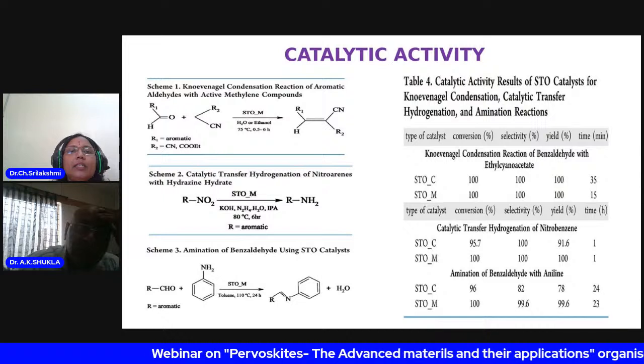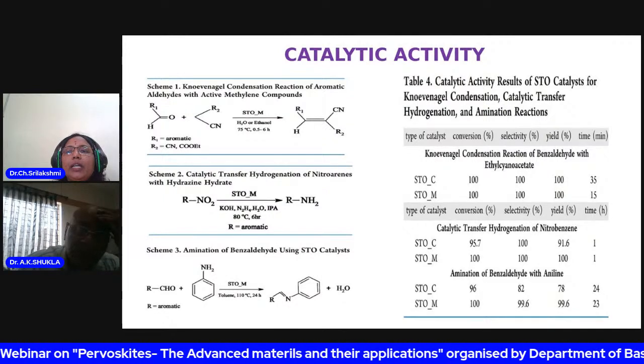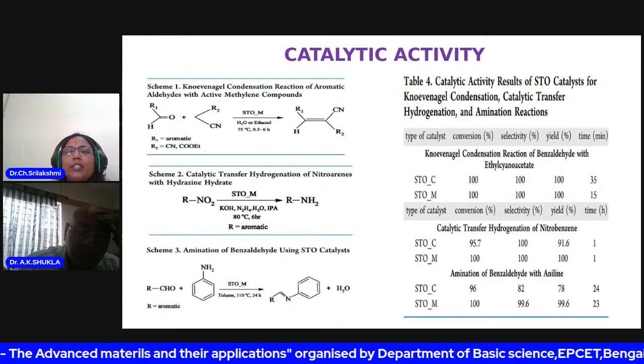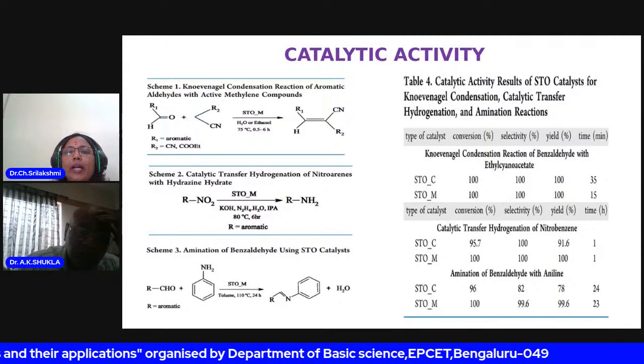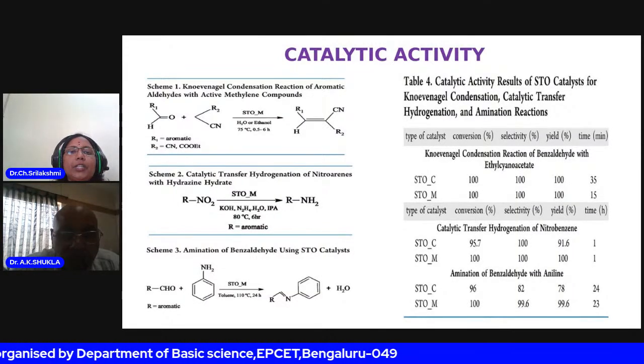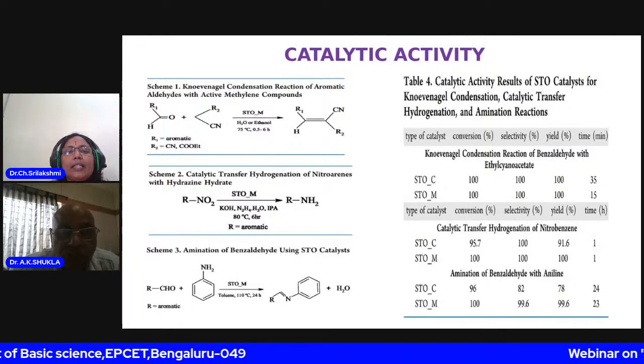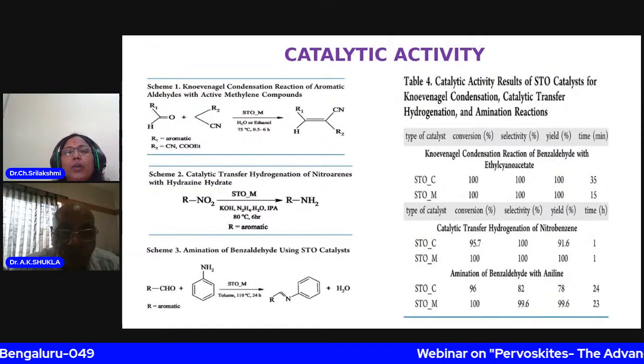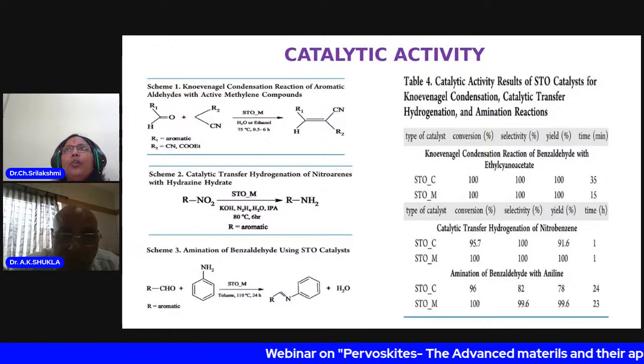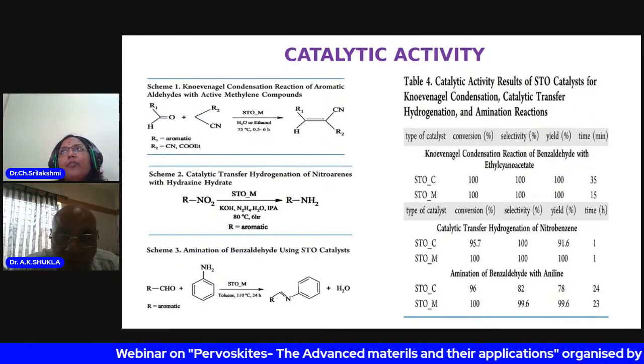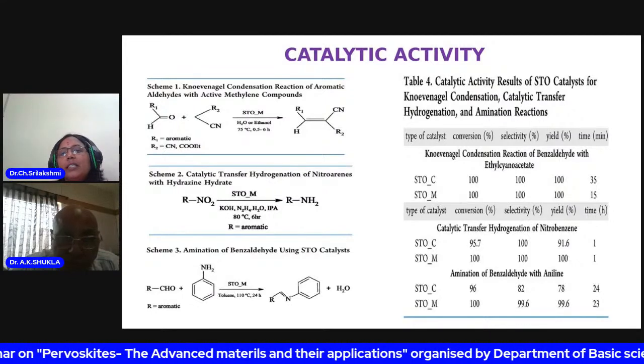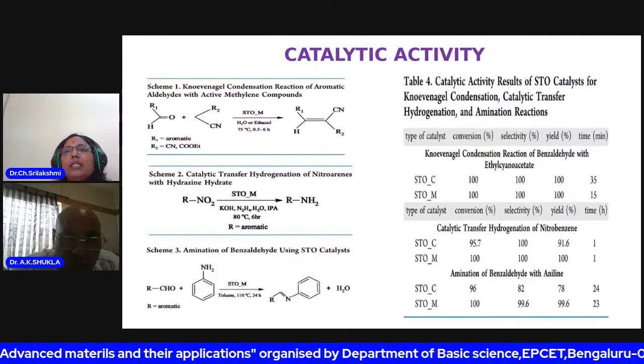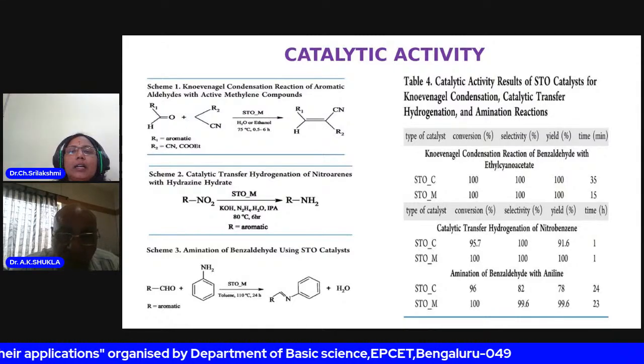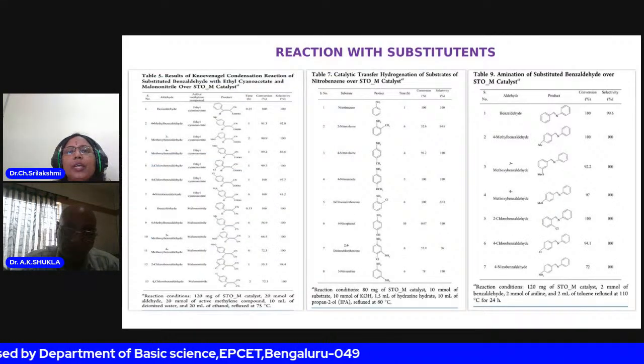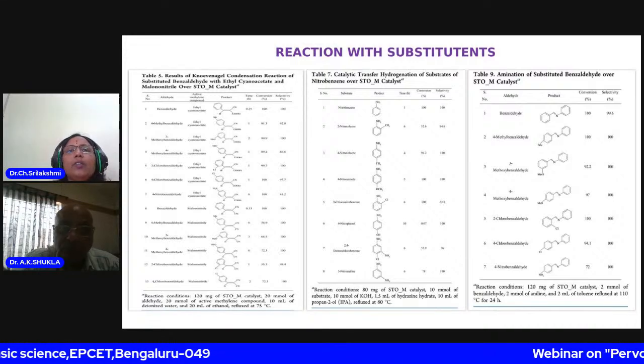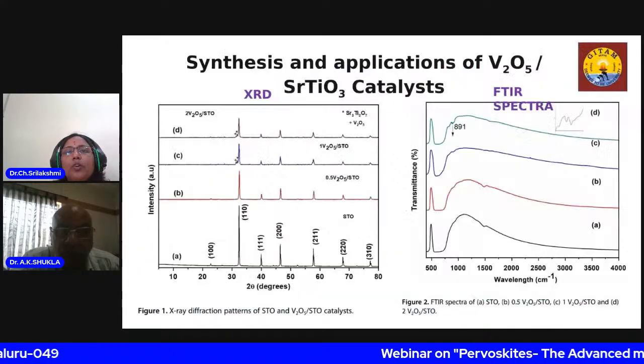Similarly for transfer hydrogenation, the conversion of nitrobenzene to aniline, the reaction was completed in 1 hour. Then amination: the reaction between aldehydes and amines gives Schiff bases. All these products are useful raw materials for the synthesis of agrochemicals, pesticides, pharmaceuticals, etc. From these results we can say that the microwave-synthesized material is excellent for any type of reaction you can explore. We have also tried other substrates, which I am not going into in detail.